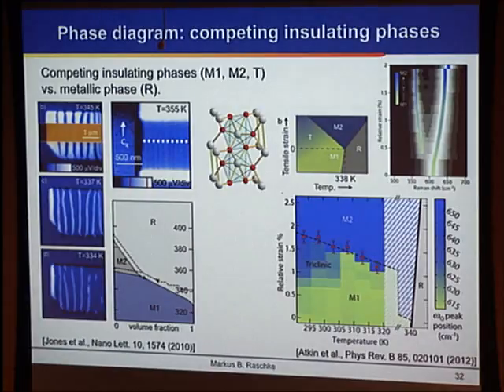So what makes this so rich, even though it is a benign-looking oxide, is that we have this fairly complex phase diagram of temperature and strain. This metallic phase in the rutile structure goes across a triple point where there are two insulating monoclinic phases, M1 and M2, and separated by a certain temperature gap is a triclinic phase. The interesting question was what happens as you go from this monoclinic M1 phase or this monoclinic M2 phase, which have slightly different crystal structures. So we mapped out this phase diagram.